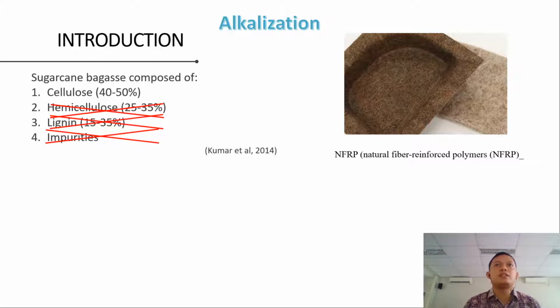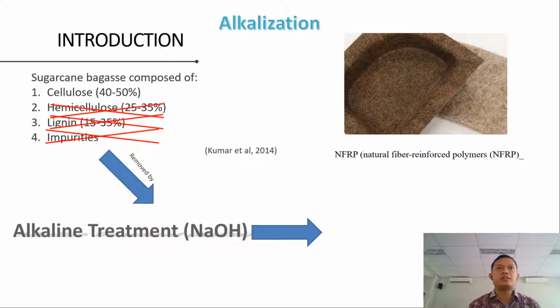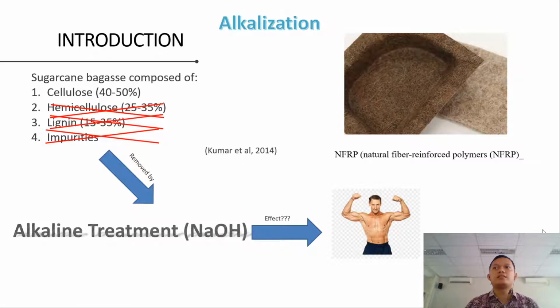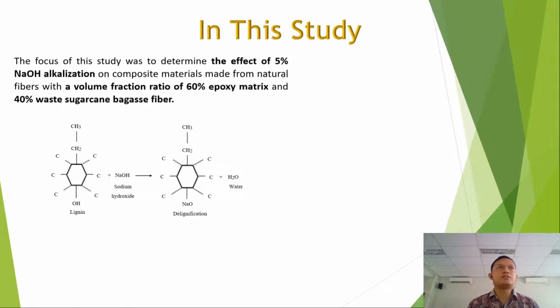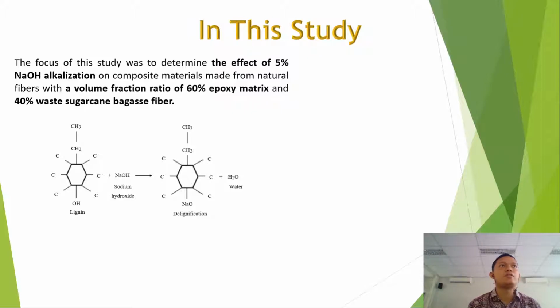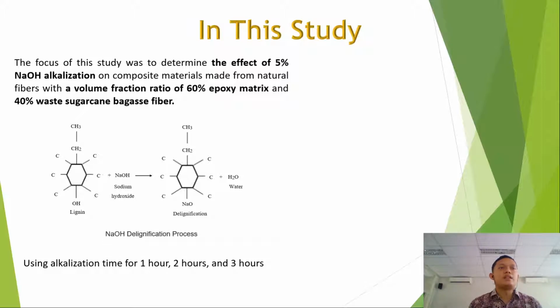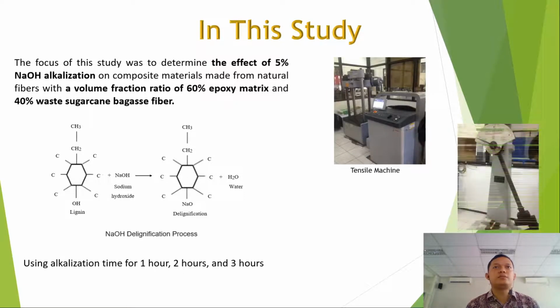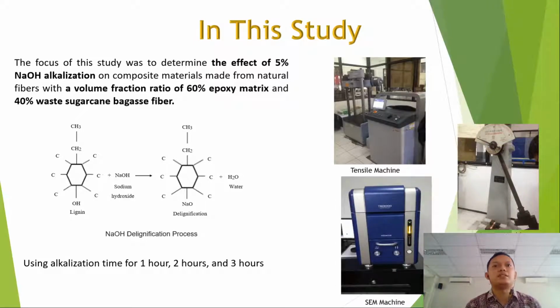And we know that natural fiber reinforced polymers, NFRP, have been the subject of several studies about combining NFC into polymer. That's why we need alkaline treatment with NaOH, to make the composite stronger, and this can increase the mechanical properties. So in this study, the focus was to determine the effect of 5% NaOH alkalization on composite materials made from natural fibers: waste sugarcane bagasse fiber 40% and epoxy matrix 60%. The alkalization time is 1, 2, and 3 hours. And our characterization uses a tensile machine, impact machine, and then SEM.